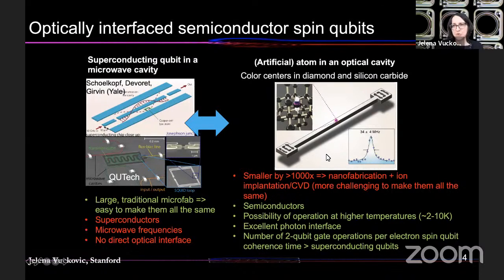But that also means that you have to use more sophisticated nanofabrication techniques to implement everything. So just inserting one atom at a special spot without damaging the lattice is pretty challenging, and I'll show you some ideas and some work that we've been doing towards solving those problems. Then you have to fabricate these structures that are much smaller, so nanofabrication is more sophisticated. But we work with semiconductors, which is good, right? So we work with more traditional materials, in particular silicon carbide, which is a pretty common material in electronics. Then we can possibly operate systems at higher temperatures, not at room temperature, but a few Kelvin, which means that we can use different instruments.